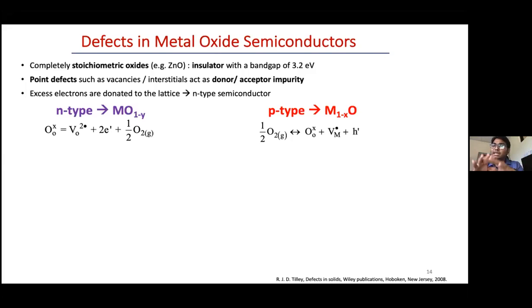So the excess charges are incorporated into the lattice to accommodate this vacancy. Effectively, when an oxygen is missing from the lattice, for an oxygen which is divalent, it will have 2 electrons donated to the lattice. Similarly, if there is a metal ion which is missing from its place, you can imagine there is a vacancy at a metal ion place, and that leads to excess positive charges in the system. In either case, we are incorporating either a donor impurity, which gives rise to n-type conduction, or an acceptor impurity, which gives rise to p-type conduction. The excess electrons would make this n-type, and the excess holes or excess positive charges are going to make it a p-type material.